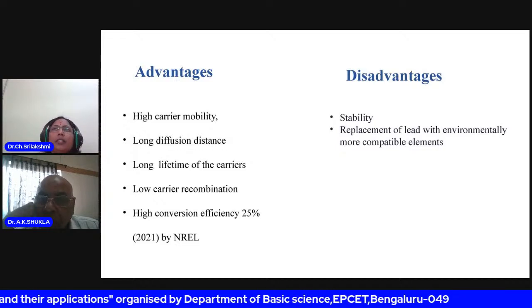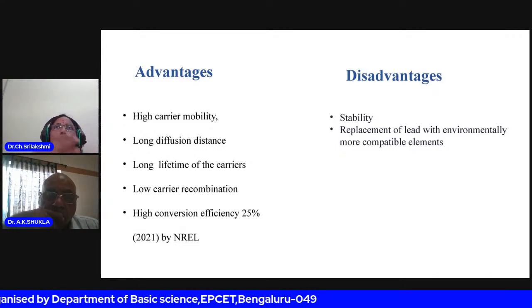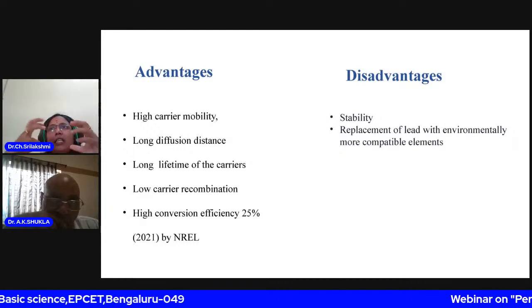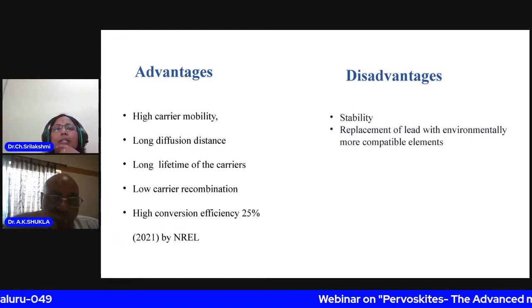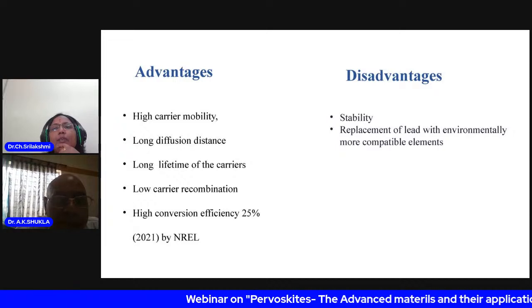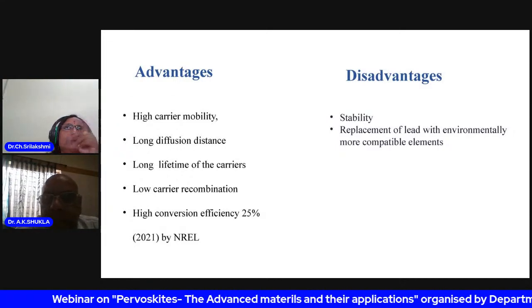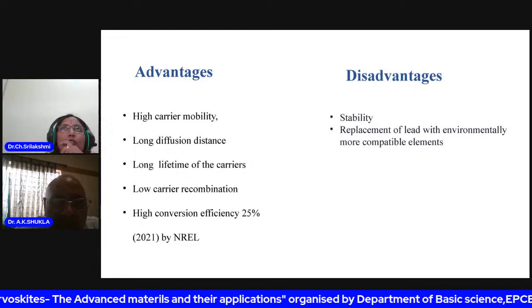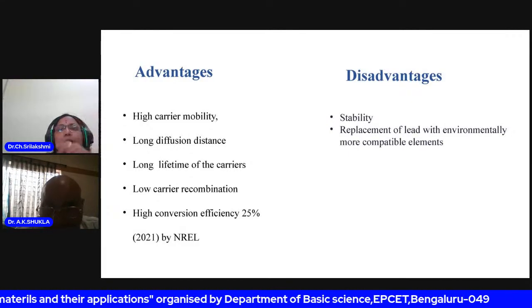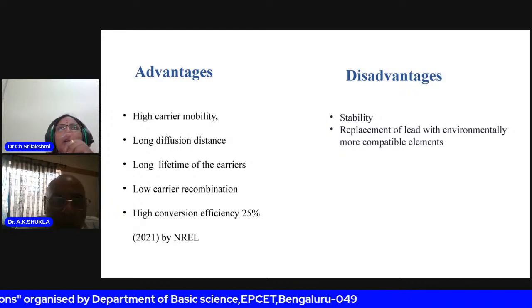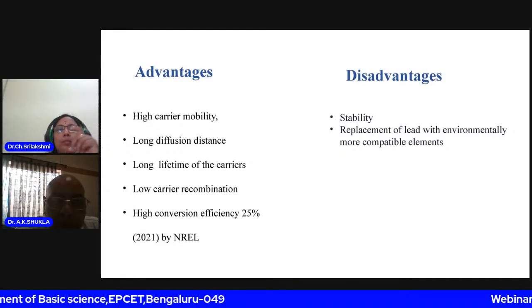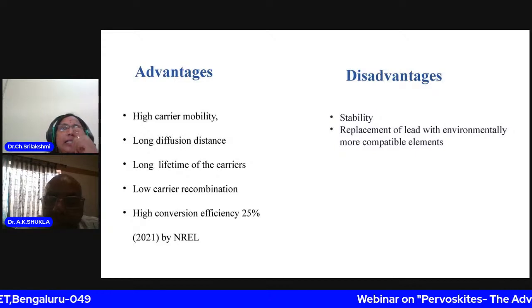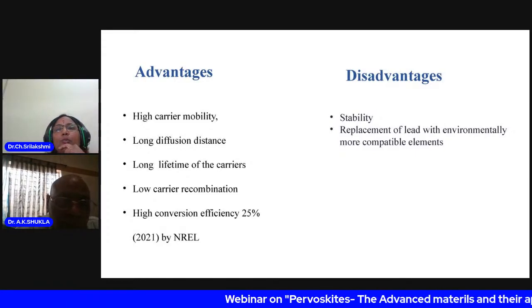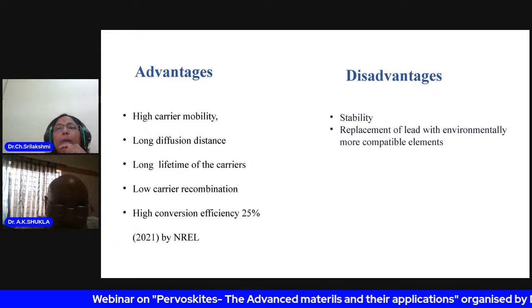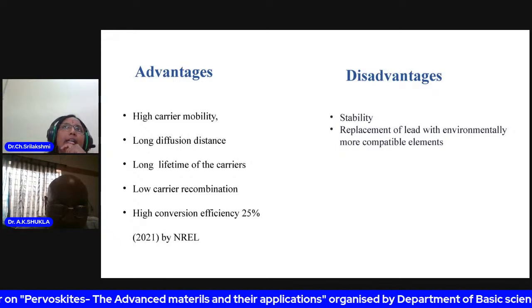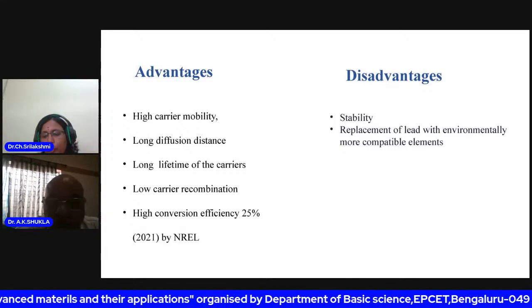But for every system, there are advantages and disadvantages. Not every single material is highly advantageous. Even though there are a lot of advantages, the disadvantage of these materials is stability. So this conversion efficiency is not stable. With time, it is going down. That's where research and development comes in and plays a significant role for these materials. And another thing is the lead. So far, lead is the most active component here. So replacement of lead with environmentally friendly elements in the perovskite material will protect the environment also.